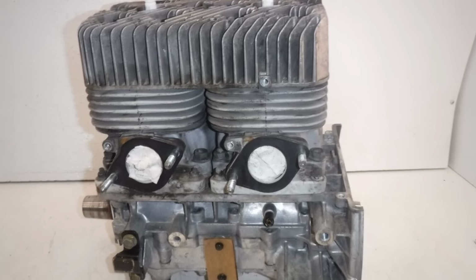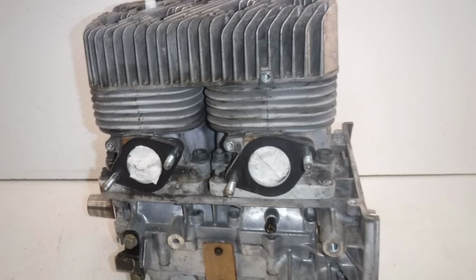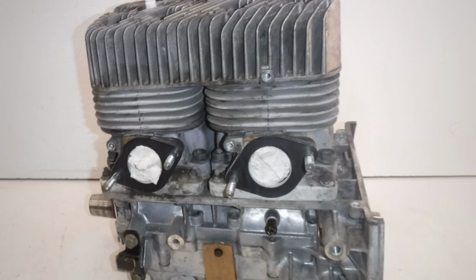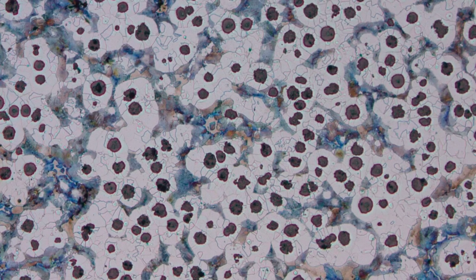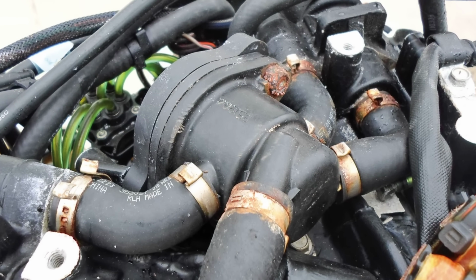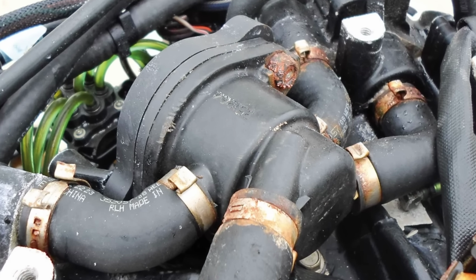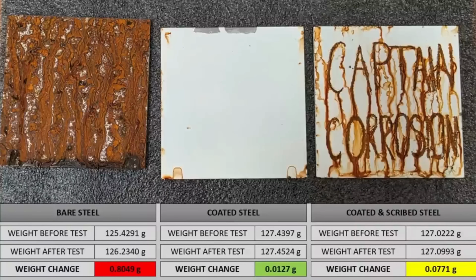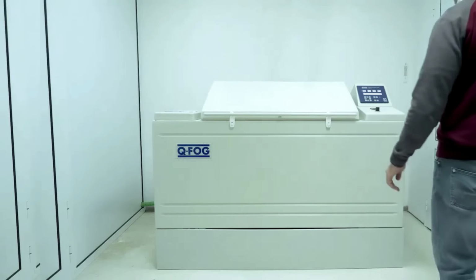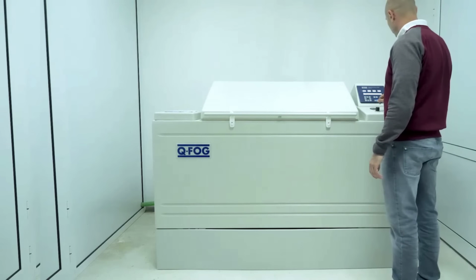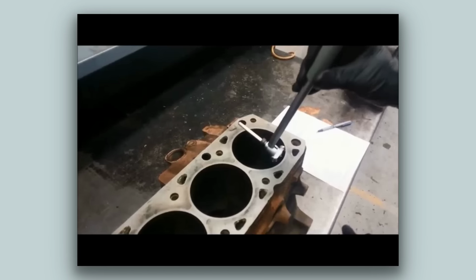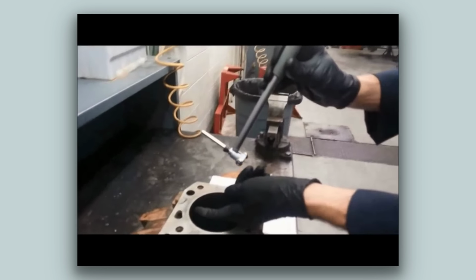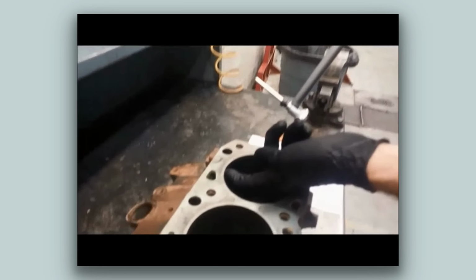The Chinese head, cast from a lower-cost aluminum silicon blend, lacks any temper marking. Metallographic cross-sections expose scattered porosity, pockets of trapped gas, and uneven grain boundaries. Where the American part shrugs off 1,000 hours in salt spray, the Chinese casting begins to pit and flake within weeks in ASTM B117 corrosion chambers. Micrometers move in, measuring critical bores and sealing surfaces.